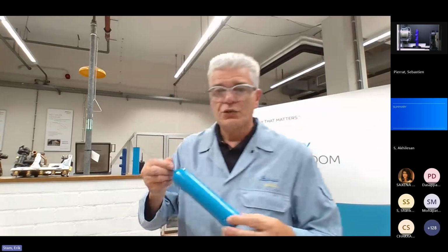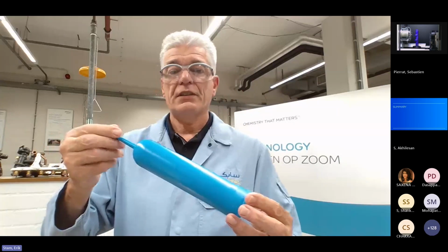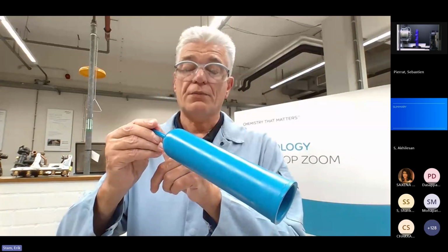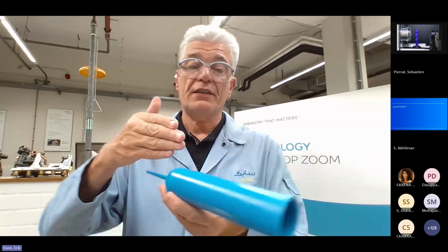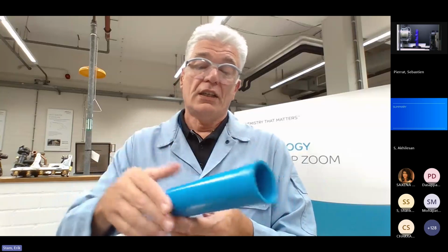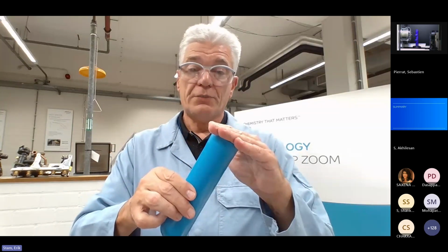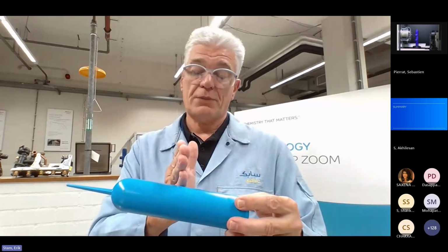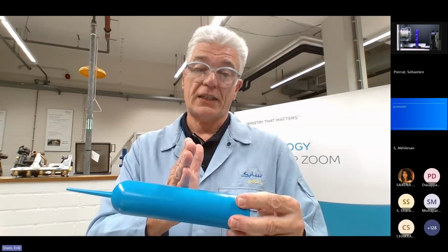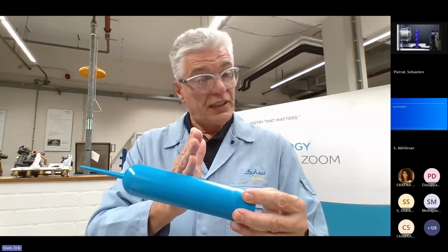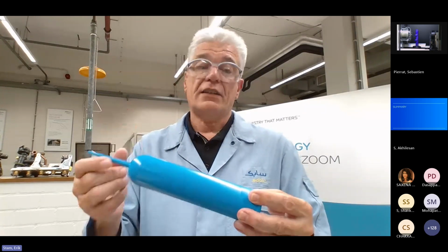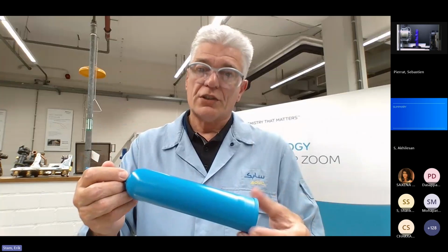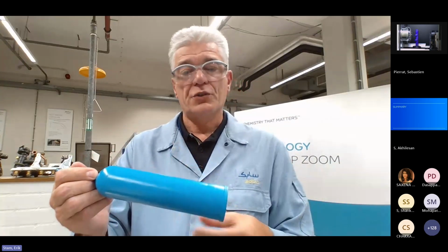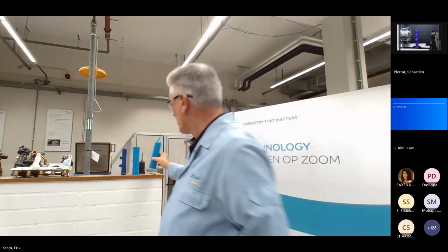The first one I want to show you is a top-gated pressure vessel. Again, it's injection molded from this side, so the fibers are orientated nicely in this direction. If you then fill this with water and pressurize, then the stresses are perpendicular to the orientation of the fibers, which means that you do not get the optimal strength as seen in the tensile bar. It will be much lower, so that's something which you also see in the application.